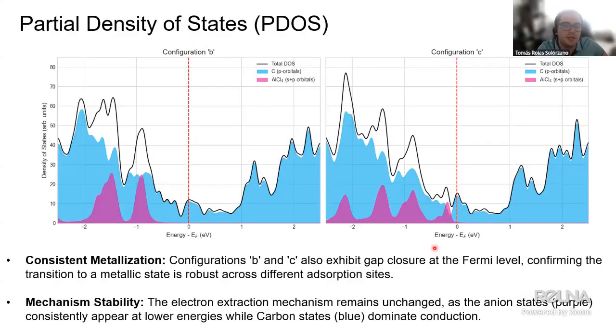Also, we can see here the other two. In these cases, which are B and C, where the scroll keeps more of a closed shape and tries to protect more the molecule, it does clearly show more of a metallic state, and also p-type doping upon the absorption of the AlCl4. So this tells us not only that the absorption is stable, but also that taking on these molecules will produce changes in the conductivity, making it more metallic in most of the cases, which will also be good for the workings of the battery cell. Then again, this is only one molecule with the system. And what we like to do is use this as the base for building a larger picture of the system.